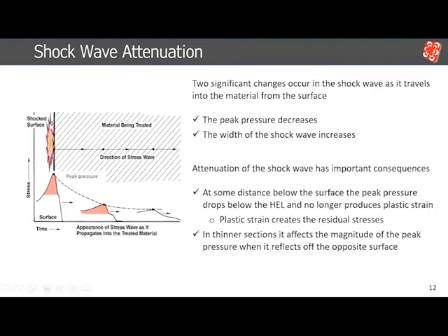So now we have a plasma at the surface that created a shock wave. When the shock wave propagates into the material, at the start you have the highest peak pressure, and that peak pressure needs to be higher than your dynamic yield strength, which is also called the Hugoniot elastic limit. As long as your peak pressure is higher than the Hugoniot elastic limit, your dynamic yield, you will be generating plastic deformation. As the wave propagates into your material, it dampens, meaning you're losing peak pressure. It keeps going lower and lower until you go below that Hugoniot elastic limit, and then you'll no longer generate plastic deformation. So now you're generating plastic deformation, and actually it's a gradient of plastic deformation up to a specific depth of effect.